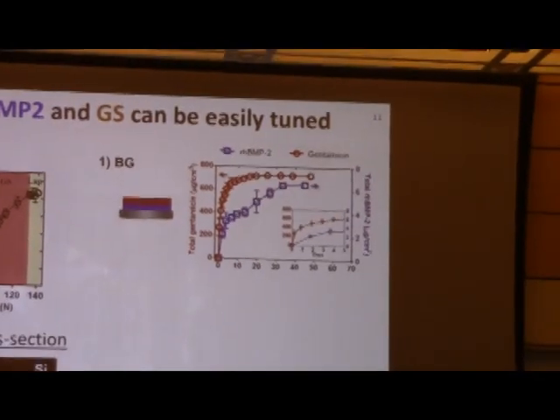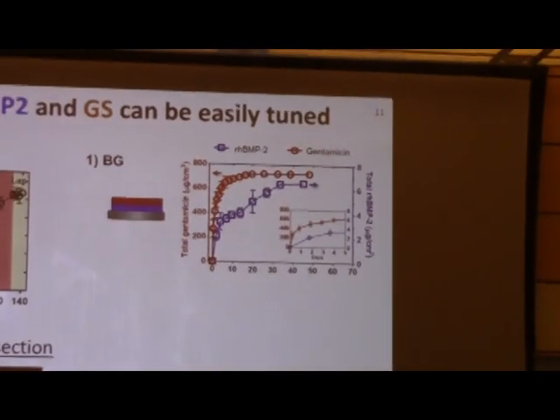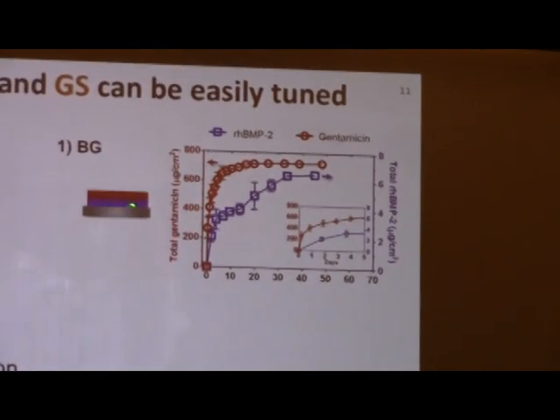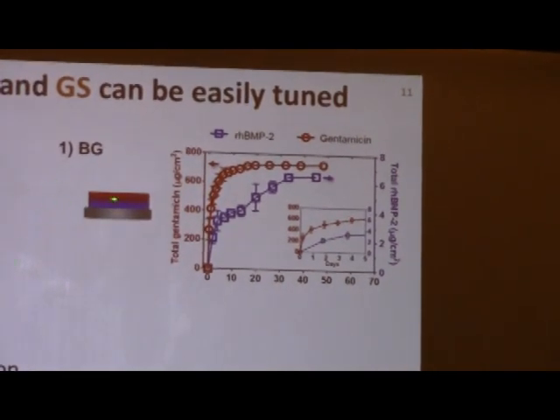When Juha looks at the relative rates of release of these two systems, what she saw was essentially that without any kind of capping arrangement, the gentamicin, which is always indicated by red, over a period of days, this is out to 70 days here, is released in a very short time frame. And the BMP2 is a little bit slower, but it comes out rather fast. So when we look at just the first 5 days, a good amount of both drugs are kind of out there, although there is some separation between the two.